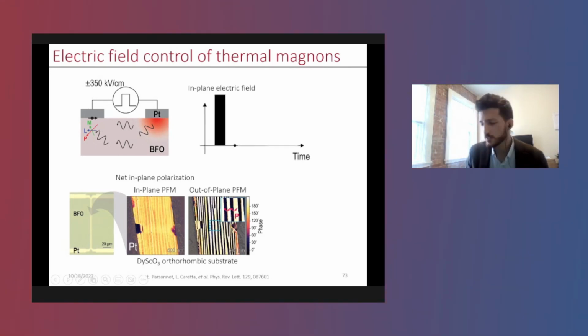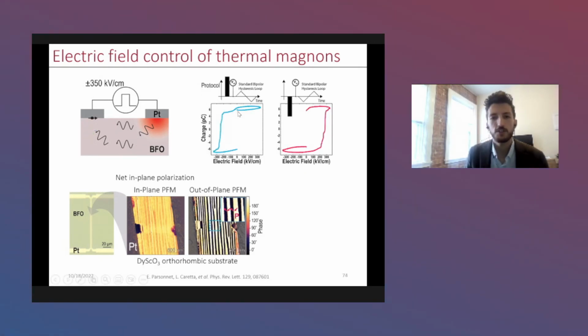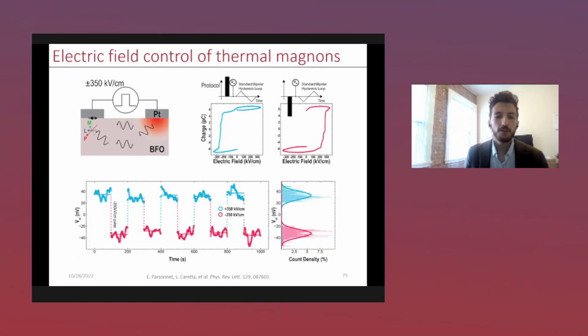And so there's a process that we use to do this. We can essentially polarize the material, measure the non-local voltage, and do some checks to make sure that we haven't switched the polarization state after we've measured the non-local voltage. Here you're seeing an experiment where we measure the non-local voltage as a function of time. We oscillate the electric field every 100 seconds. You can clearly see that we get 2 different distributions depending on the voltage applied that actually change sign. So we can change the sign of the non-local voltage just by applying an electric field.